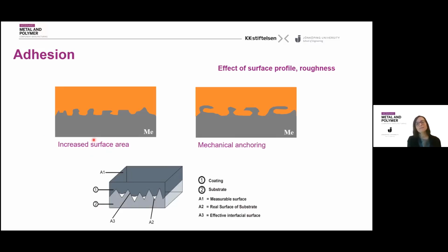Additionally, but difficult to perform, we can create a special profile by roughening to add a component of mechanical anchoring. In order to have mechanical anchoring, it's not enough to have a rough surface. The surface should provide a geometry where real geometrical blocking can be done between the materials, which is not so simple to perform. Nevertheless, roughness is really important to increase the number of bonds we perform.